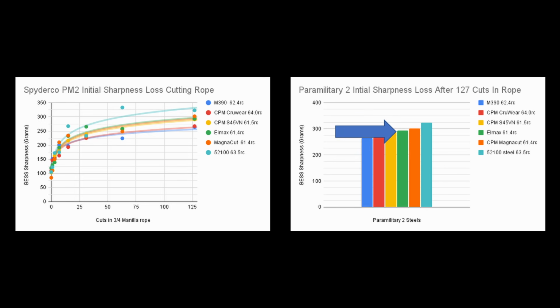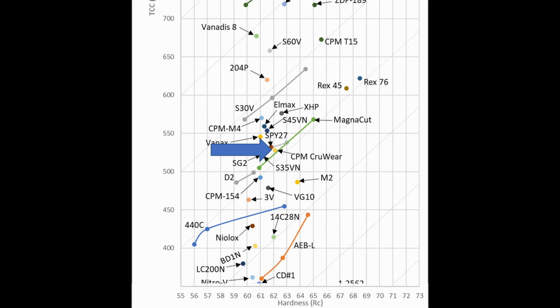S45VN, Elmax, and MagnaCut were similar to each other around 61.5 Rockwell, and also performed similarly on rope. However, S45VN and Elmax have slightly better wear resistance than MagnaCut, and also lasted a bit better after 127 cuts on the rope. M390 was the most wear-resistant steel tested and was also relatively high in hardness at 62.4 RC. CPM CruWear has somewhat less wear resistance than M390 even at this high hardness of 64 Rockwell, but because of its excellent combination of strength and wear resistance, it actually nearly matched M390, even though M390 has somewhat better wear resistance. CPM CruWear and MagnaCut have very similar wear resistance, so we would expect 64 Rockwell MagnaCut to perform similarly.